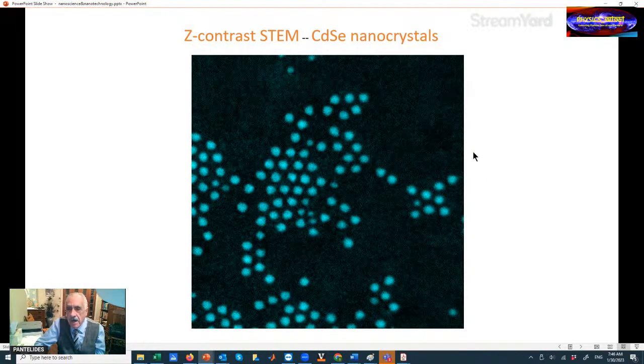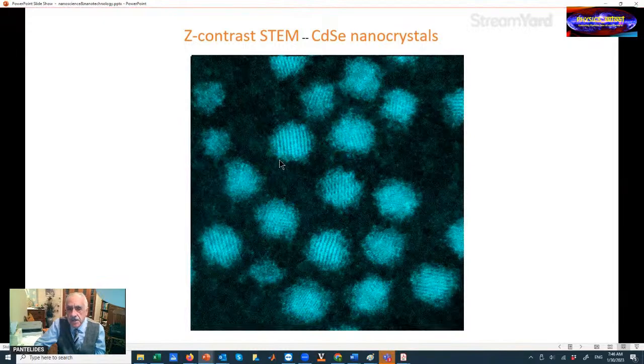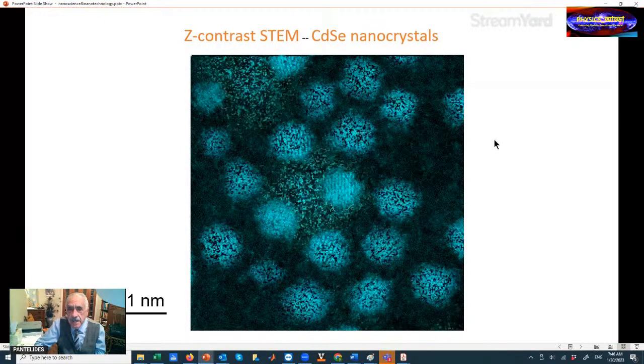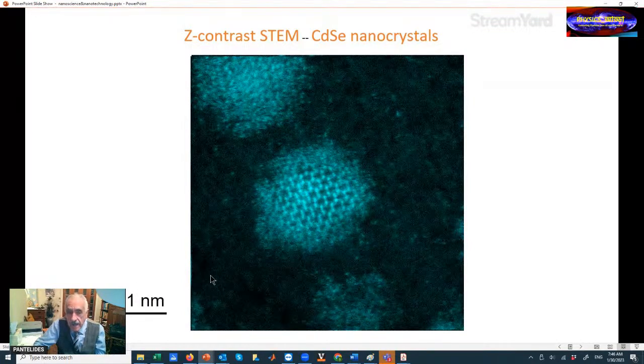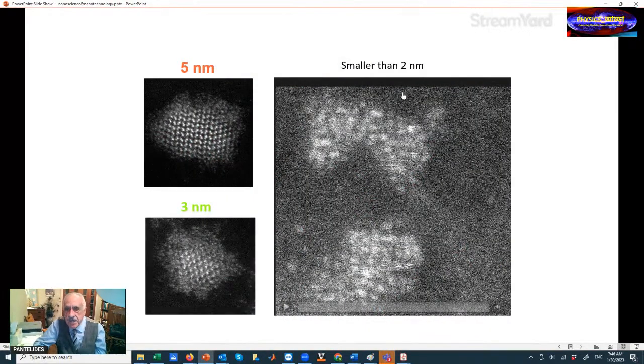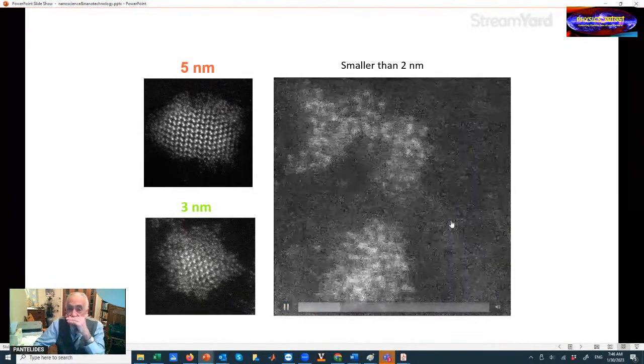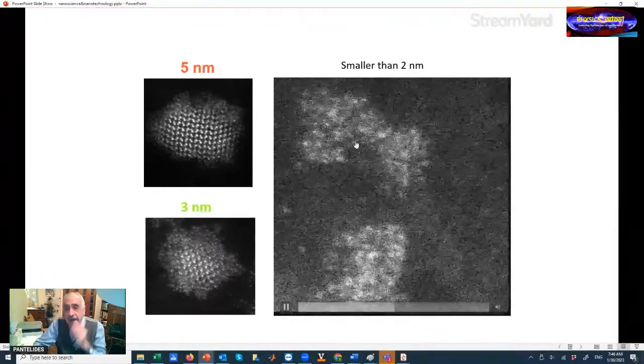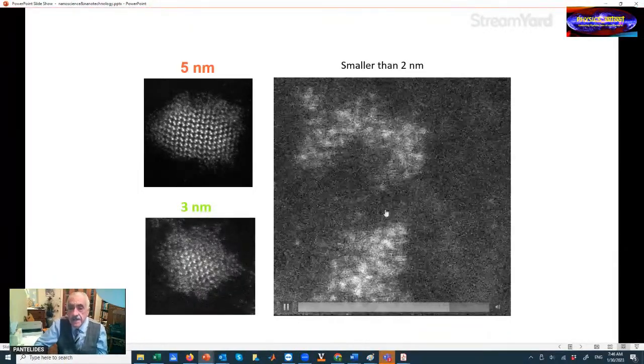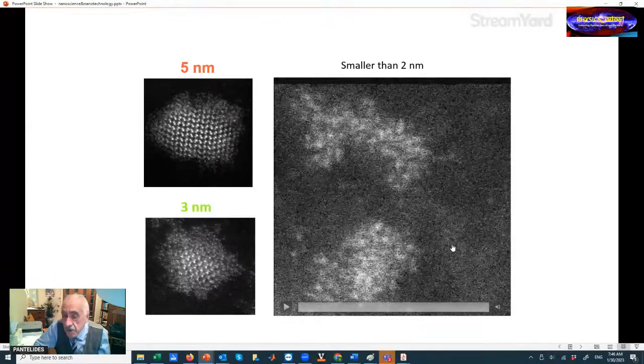Here are the nanoparticles. You can see how uniform they are. And when we look at them closer with the microscope, you can start seeing their crystalline structure. And even closer, this is the scale for 1 nanometer. So these are larger than 2 nanometers, and they are crystalline. And then they get fuzzy at the edges. But when you get smaller than 2 nanometers, they are not crystalline anymore. And you can see also that they are very fluxional. They made a video of them, and the atoms are bonded together, they stick together. This is 2 different nanoparticles, but they are very fluxional again. Remember the fluxional from the gold nanoparticles.